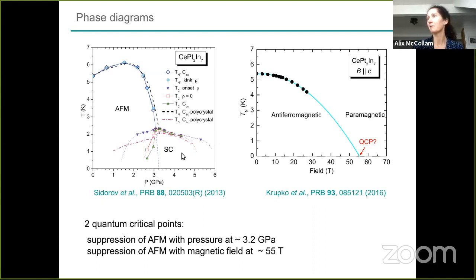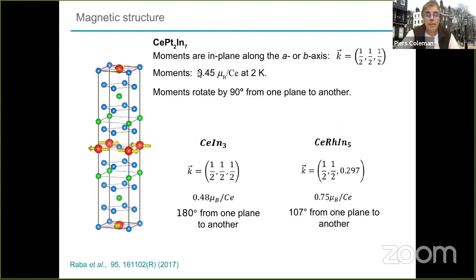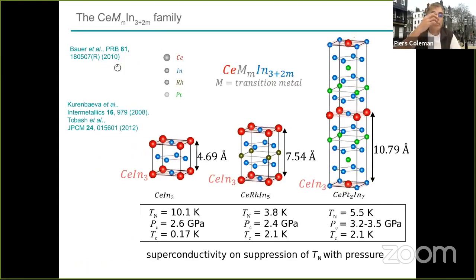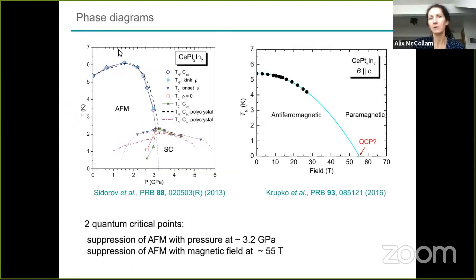Yeah, that's kind of as much as I can say about the superconductivity in cerium platinum 2 indium 7. It hasn't been measured very much, so this material is not even a fraction as widely measured as cerium rhodium indium 5. Good single crystals only became available, I think, a few years ago, and even then not so widely measured. So apart from knowing that the superconducting dome looks kind of like this, and that there have been a few measurements,